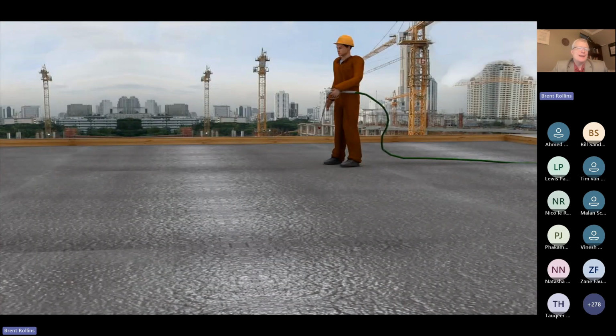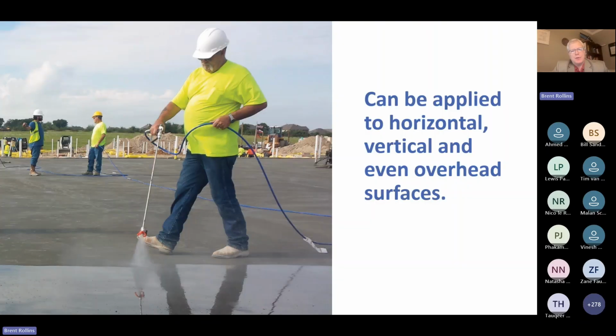Colloidal silica can be put in the mix, but most often what we see effectiveness-wise is to apply the colloidal silica by spraying to the concrete surface where it enters the concrete. Again, its small size allows it to get deep, and what we've seen in the laboratory on a very dense mix with about a 0.30 water to binder ratio is 38 millimeters on a 100 millimeter slab is the least that we've ever measured. We usually see somewhere between a half to a third the depth of the concrete member, and it can be applied horizontally, vertically, or even overhead.